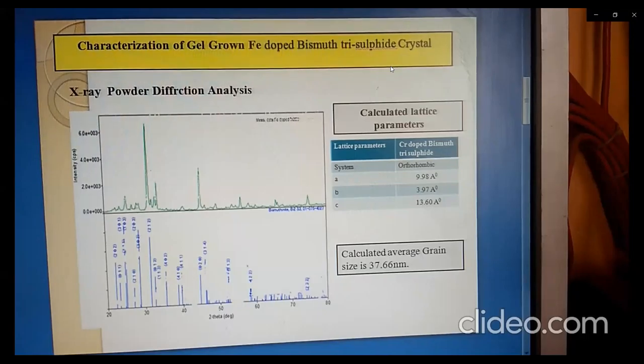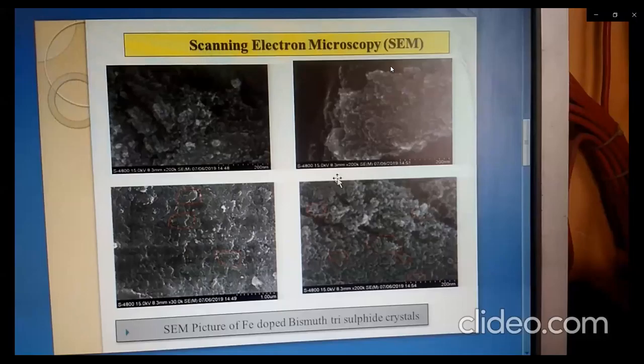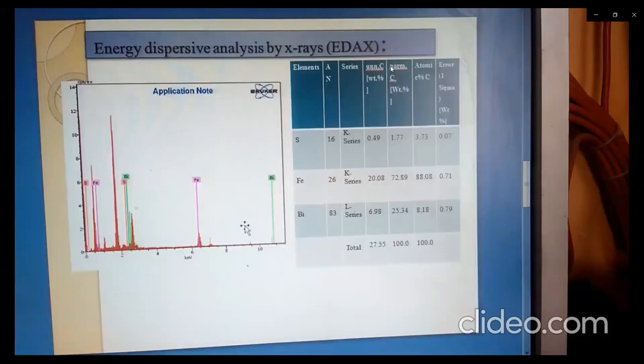Next characterization is SEM. In the photograph, particles have spherical aggregate shapes. Some microstructure appears heterogeneous and porous. Here, the surface morphology is affected due to the doping. Another characterization is EDAX. In the EDAX spectrum, the peaks show the presence of iron, sulfur, and bismuth in the grown crystal. This is a clear indication of the presence of iron doping in the crystals.